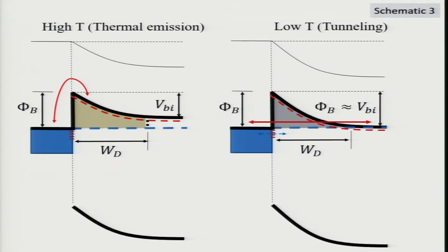And now, for high temperature, the process of getting over the barrier is usually by thermal emission. It's this over-the-barrier process, so you're at finite temperature. This is the width of the depletion layer, and this red dashed line represents the density of essentially your impurity levels. If you lower the temperature, this is the silicon impurity band. We're going to use silicon impurities, and we're going to use mainly in this talk gallium arsenide because the silicon impurity level lies very close to the conduction band, around 6 millielectron volts away. So we can go down. We have lots of ionized donors in the conduction band, and the material conducts and doesn't freeze out, all the way down to 3 or 4 degrees Kelvin.